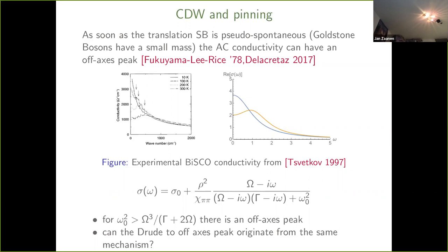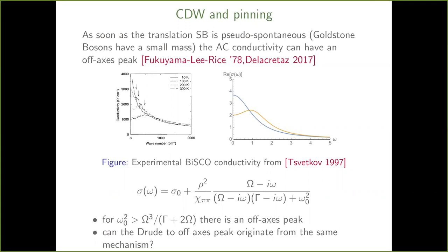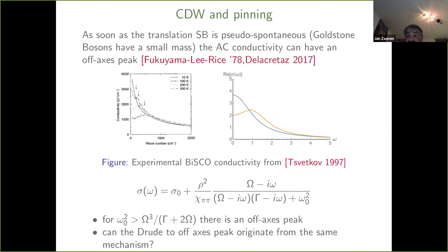But the fact that the Drude width is Planckian, doesn't that make it a little harder to interpret as definitely Drude? If there's an overlap with a conserved quantity, you'd expect a sharper peak. The analytic form is Drude, a half Lorentzian, right? When you have a half Lorentzian, you have a width, and that is the Drude width related to momentum relaxation. By definition, it has to be nearly hydrodynamical. The momentum is nearly conserved because the width of the peak is small compared to anything else at low temperatures. And then the total area under the Drude peak is the Drude weight, and that is temperature independent. These are all classic facts. Tanner already made these cases in the 1990s.